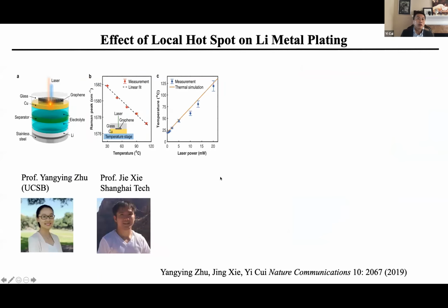Let me give you one example of what issue temperature inhomogeneity can create. In this experiment we conducted, we used a local laser to heat up the current collector on the anode side, so you have a local hot spot. And we could use graphene on the top surface, using the Raman shift to indicate the temperature there. It is a linear relationship between the laser power and the Raman shift.